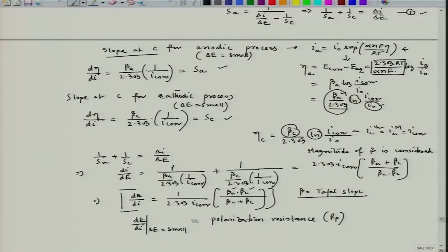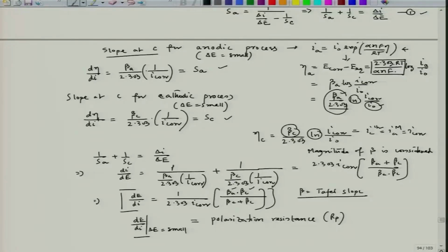Interestingly, if we know βA and βC, then we can find out the corrosion current density. But even if we do not know βA and βC, by doing a small experiment of fluctuating the polarization within plus minus 20 millivolt, we can get the slope for that linear line, and that slope gives me the polarization resistance. That means the higher the polarization resistance, the higher the corrosion resistance, because the more the polarization resistance, the lower the possibility of ion formation. So that is what RP gives, a relative behavior. If we consider two metals in an electrolyte and one metal has a very high RP, we can definitely say that metal has a very high corrosion resistance in that solution.